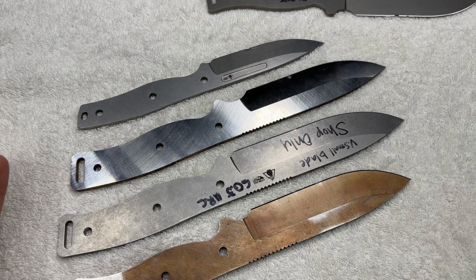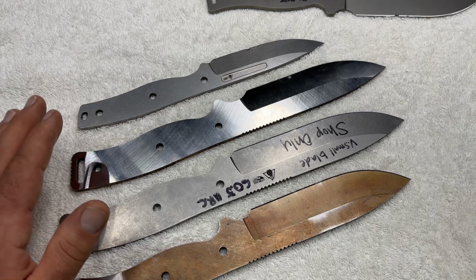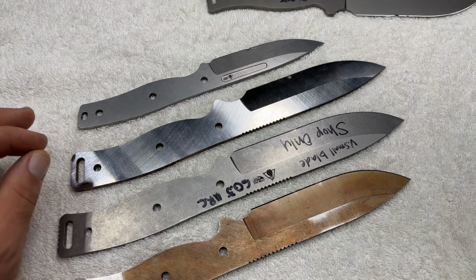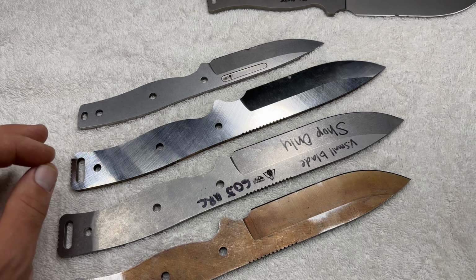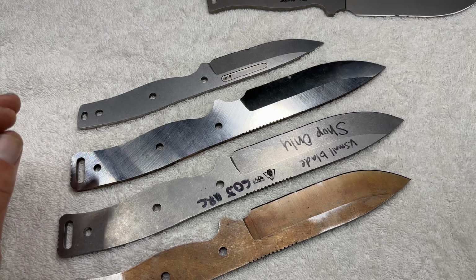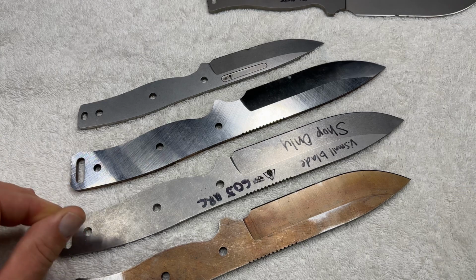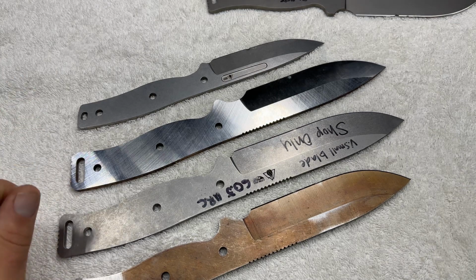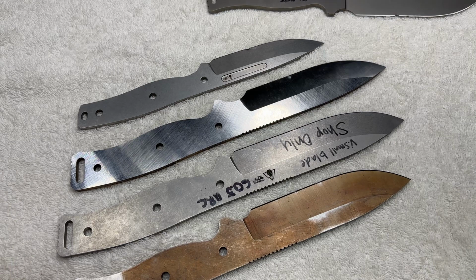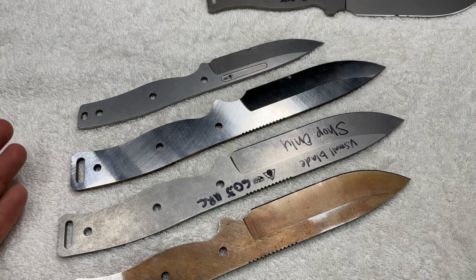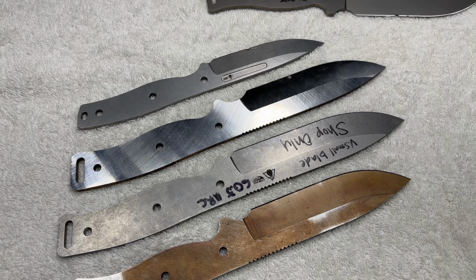And we've milked everything that we can between Nathan and some of the different people around in the industry. We're pushing the limits of what this material is capable of, and it's to the point where it causes part warpage and extra handling and a bunch of just additional headache to try and get that result we're looking for. That's where I started looking over the pond at Böhler Uddeholm and saw the K890 grade, and they seem receptive to that, where after some conversations with the folks at Niagara and Crucible, I don't think that with any reasonable time frame we're going to see any real innovations or improvements to this formulation.